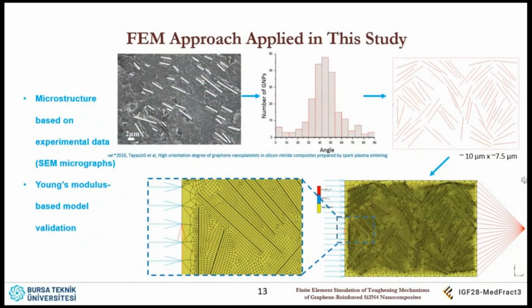So I wanted to suggest a new approach for this purpose, to simulate the toughening mechanisms. I have done no experimental work. I don't have any facility for this. I am new to this field. So first, find a microstructural image, and this study provides the statistical distribution of the nanoplatelets, and apply it in my models. So I apply the distribution in the computer model. This is the zoomed in view. There is a graphene phase, and there is a matrix phase. So this is based on experimental data.